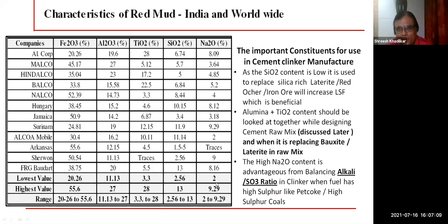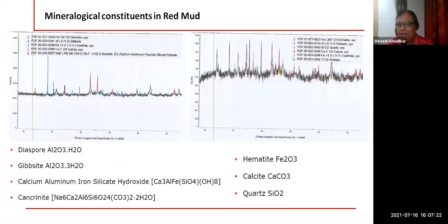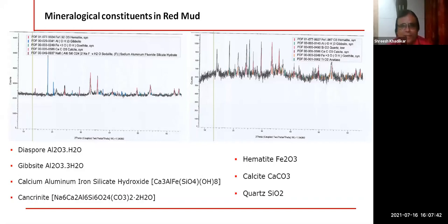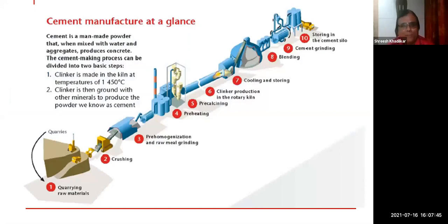Red mud composition is similar to corrective materials used in clinker manufacturing. Its lower silica is an advantage; its higher alkali is also an advantage. The mineralogy of red mud is relevant — for those with a cement background, portland clinker has higher lime, lower silica, alumina at four to six percent, and iron at three to five percent.